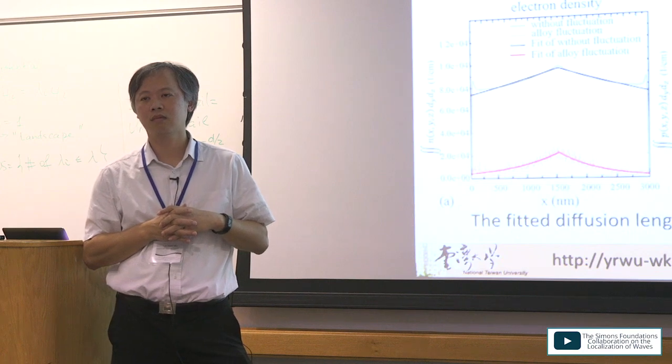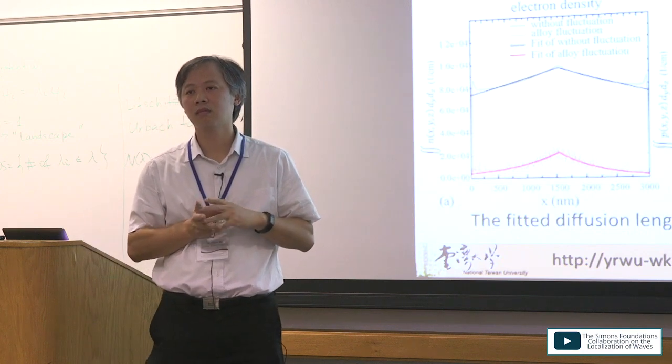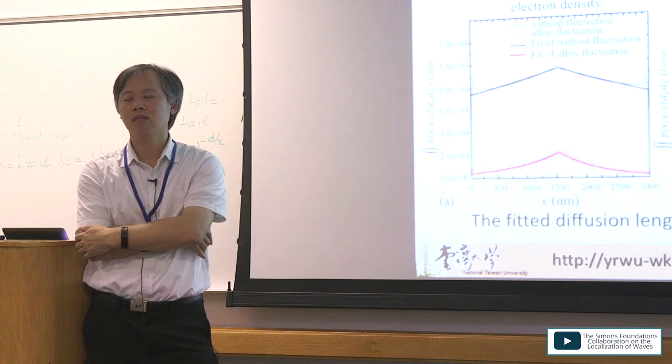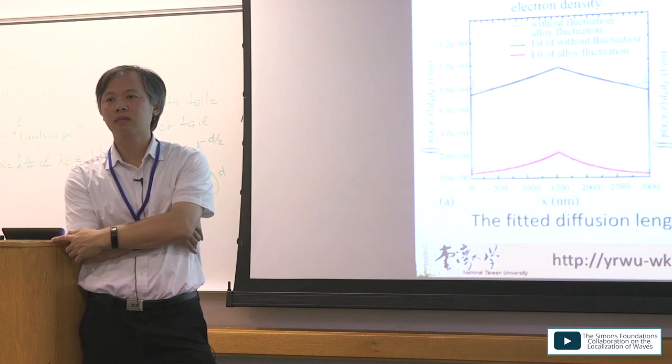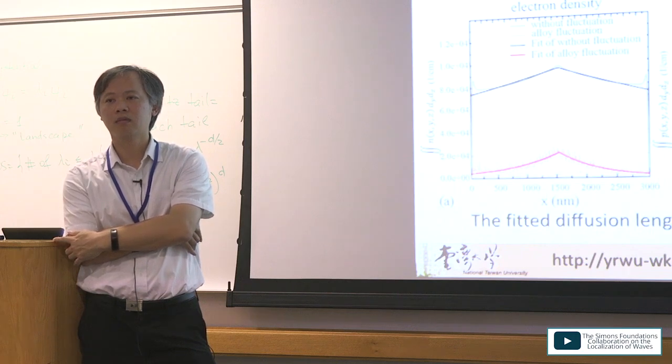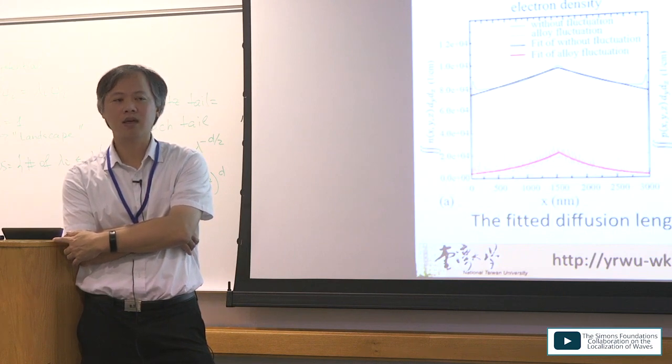If you average over a certain area, this angle rearrangement can be taken out, and you can again use the strain formula of the homogeneous material. So I fully agree that you should do this average, but I think that's another way of looking at this angular redistribution. Just as a comment.